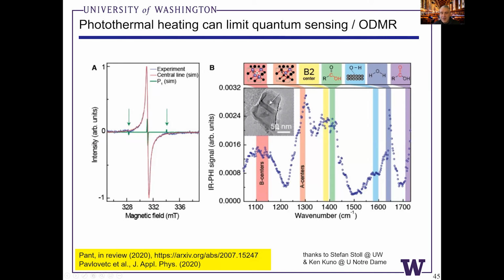We think there may be also some A-center aggregates. This could possibly be an A-center, sort of a nitrogen cluster in these materials. We're not quite sure. This could also just be strain and some contrast effects in the bright field image. But this is an EPR spectrum conclusively proving that there are P1 centers in these materials.